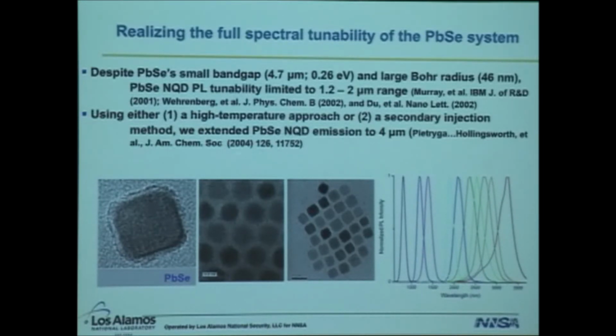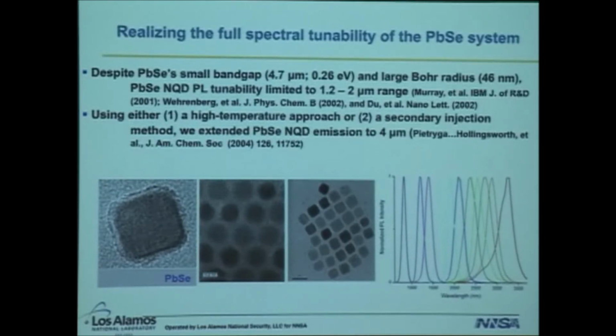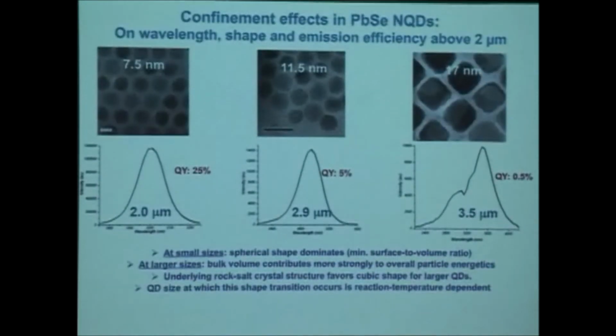So lead selenide is a nice material in that it has a bulk band gap around 4.7 microns and a very large Bohr radius. So that means that you don't have to go to very, very small sizes to achieve strong quantum confinement effects. So you can get a lot of spectral tuning even at fairly large sizes. So it's a nice material to work with.